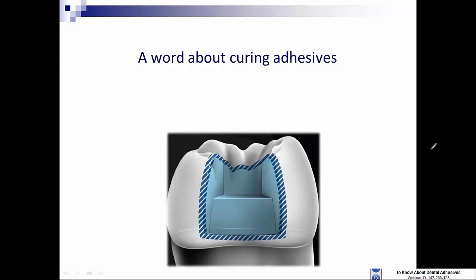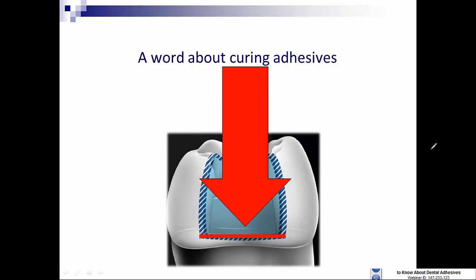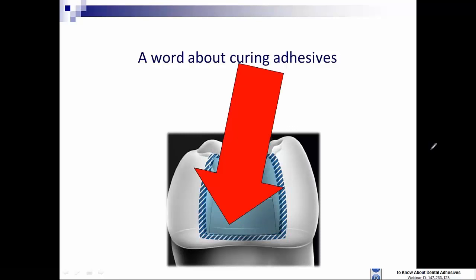Now, just a brief word about polymerization. We've all been told and taught that the most vulnerable part of a class 2 is that gingival interface. And so applying the adhesive agent in that area well, and also photopolymerizing that well, is very important. Now we know that when we put the light on top of the tooth, we're assuming that light is getting to all of that adhesive, because if the tooth glows blue, we think that every part of that tooth is getting equal energy. But if we slightly adjust our light, we can get areas of the adhesive that are under or unpolymerized. Unpolymerized adhesives on a tooth are soluble, even if you copolymerize composite resin on top of it.